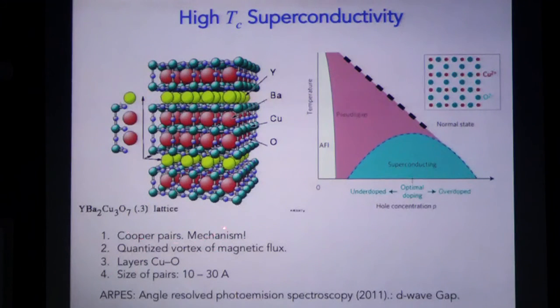Here, in these lines, there is a summary of the known facts. It is known that conduction occurs by Cooper pairs. That is, the conduction is also with pairs of electrons, but we don't know which is the mechanism behind the formation of these Cooper pairs. Under the presence of a magnetic field, what is observed is the formation of quantized vortices of magnetic flux. The conduction occurs in layers of the copper and oxygen planes, and the size of pairs is of this magnitude. Also, another characteristic phenomenologically known from high-Tc superconductivity is that this is of d-wave type. Why d-wave? I will tell you why d-wave.